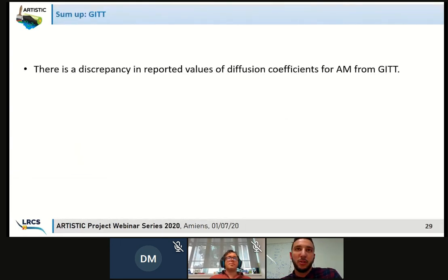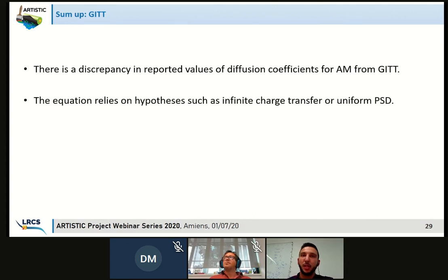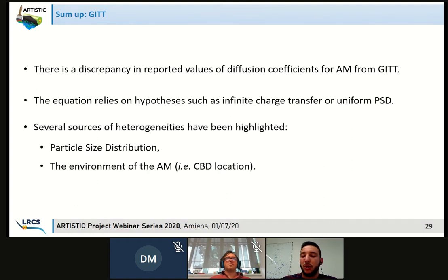So to sum up, we've seen that there was a discrepancy of reported values for diffusion coefficient. In our case, it was NMC 111 in the literature. So this equation was relying on hypotheses such as an infinite charge transfer or uniform particle size distribution. But thanks to our simulation, we will provide for the first time insight on why it's not obvious, not all the time true, and we should be wary when using such an equation, because the particle size distribution will have a huge impact on the distribution of your lithium concentration, and then on your gradient, which will have an impact on your diffusion coefficient. And also the environment of your active material, because one of the hypotheses is that your active material particle is fully exposed to electrolyte, but in a real electrode, obviously it's not the case.